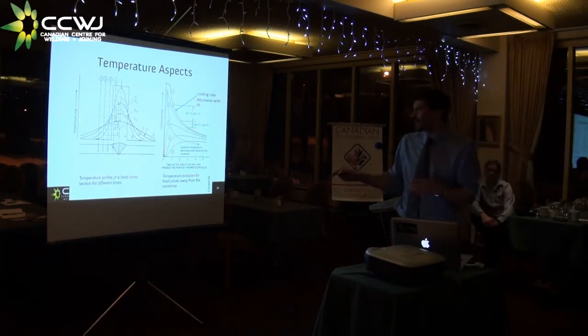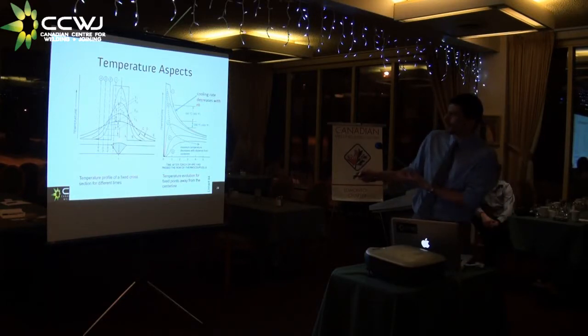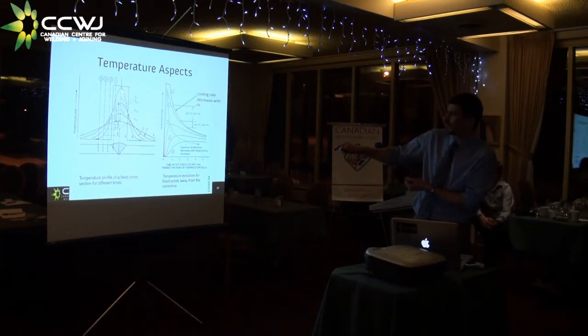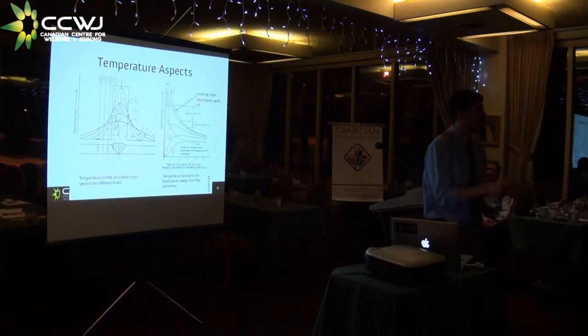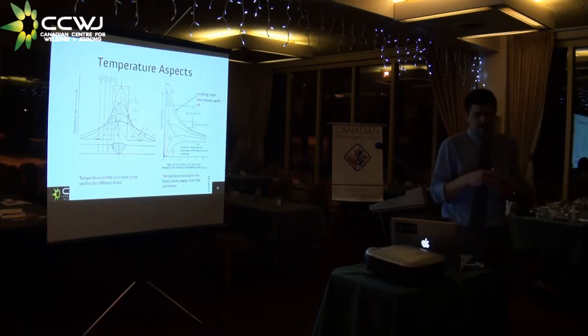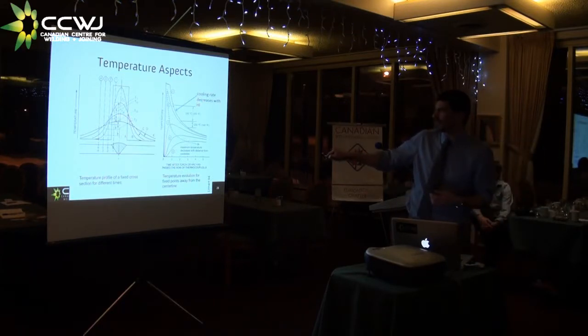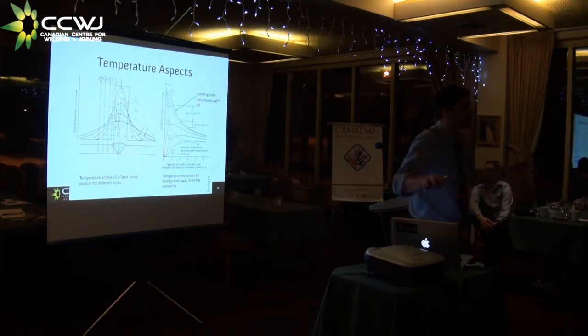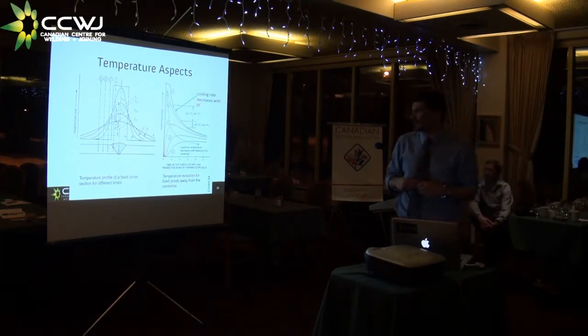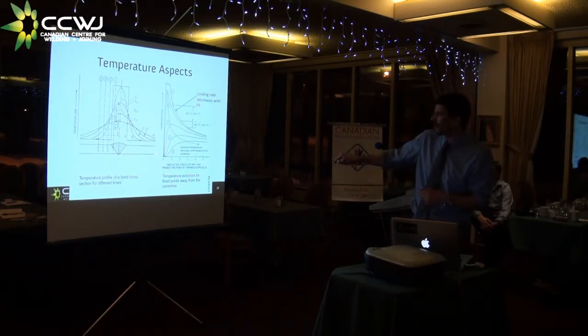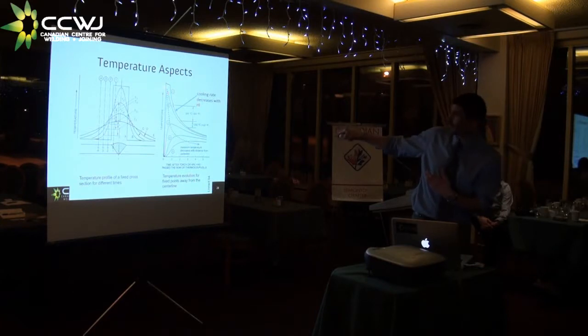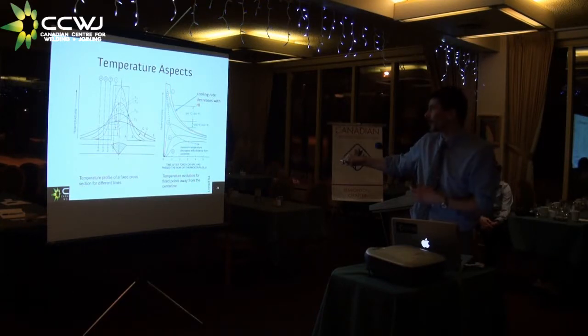Temperature aspects. So here's the funny thing of welding, right? Here you have temperature profiles. The high one is right under the arc. And after the arc passed, the temperature dissipates around. And you can calculate all this. If you're right under the arc, you get this big spike in temperature, and then it cools down slowly. And here is where you have your cooling rate and the T8/5.